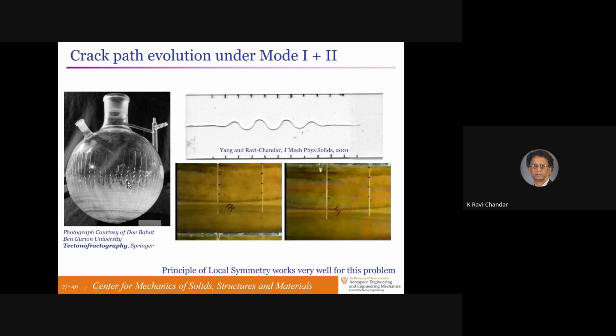The way this was accomplished was he took this glass jar, heated it up when it was empty, and then poured cold water in it. And as the cold water level was rising up, cracks started somewhere down at the bottom, and they propagate along the sides of the flask. And when they come to a certain point, they oscillate, very nice sinusoidal oscillations, and then straighten out and do various things. We did some experiments on microscope slide glasses.